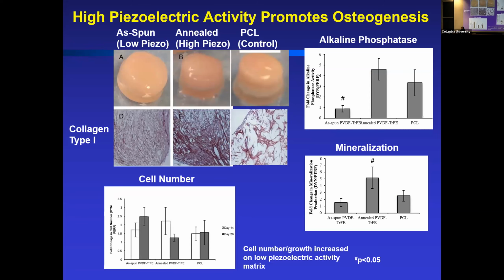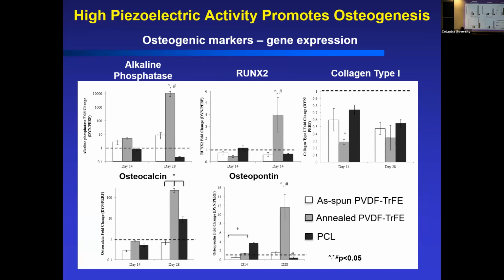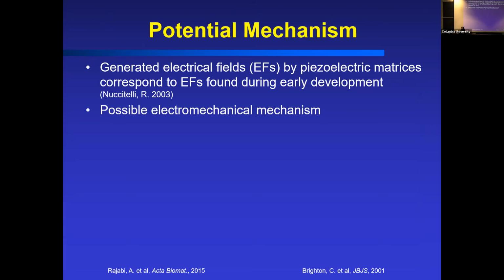So that type 1 collagen that we saw, when you looked at some additional markers and mineralization, that was there. So that annealed higher piezo gives you that. And then we look at different markers, gene expression, the RUNX2, alk-phos, osteocalcin, all those things are expressed at really high levels on that high piezoelectric, the active material. So this allows us to do a few things. We can design our scaffolds now. Again, if we go back to our osteochondral defects, we can have the higher piezoelectric material sitting in the bone, the lower piezoelectric material sitting in the cartilage. So we can think of it from that.